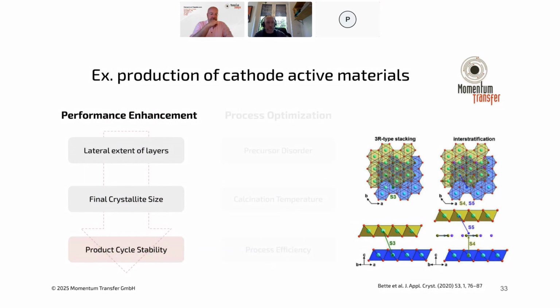And X-ray diffraction is extremely useful in characterizing these systems during processing and production, because it can give very detailed observables that help to predict the performance of the material and also how best to optimize the processing. So one example is the lateral extent of the layers. If you look on the right-hand side, on the bottom, you see the layers going horizontally across the page and how they stack together. And the dimensions of that lateral crystallite are really important to predicting the cycle stability of the material. And so by measuring that, you can already predict whether a product is going to perform well or not.